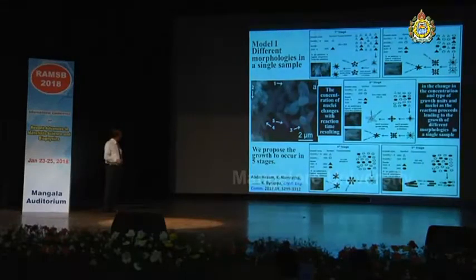And we have proposed two different models for understanding the formation of these different morphologies. Model 1 comes with 5 different stages. Of course, these are based on the concentration of the growth units. The concentration of the nuclei changes with reaction time, resulting in a change in the concentration and type of growth units. We have these two types of growth units, shown here as zinc hydroxide and zinc oxide, and the nuclei also change as the reaction proceeds, leading to the growth of different morphologies in a single sample. This is how you can see the different stages, how we can get these rods at the 5th stage.